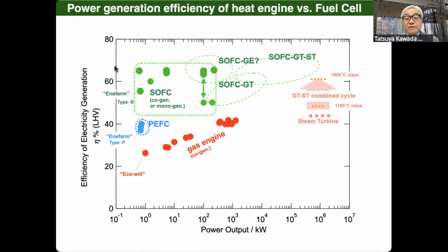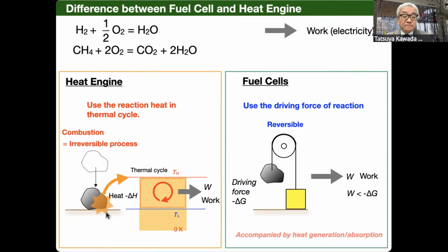So it is comparable to or higher than the highest efficiency of the heat engines and gas turbine, steam turbine combined systems. This is because the power generation mechanism is quite different from the heat engine. A heat engine uses the irreversible heat from combustion, and that heat is utilized to make the thermal cycles. But a fuel cell extracts the driving force for the reaction, that is, the Gibbs energy change directly from the fuel combustion reaction. So this is kind of a reversible system,